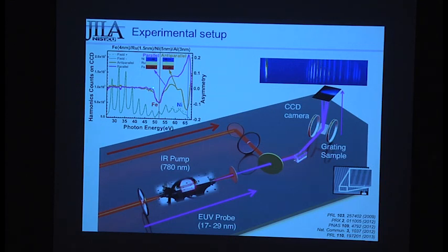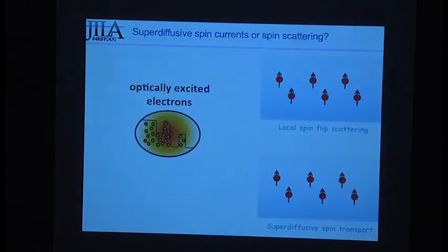And so this is a magnetic asymmetry plot. It is flat everywhere except at the iron M and nickel M edges. So it lets us monitor very sensitively, at the same time, what the magnetic moment is in each of those layers. Thanks, Isaac, for the question.